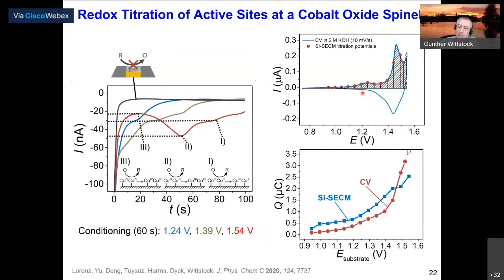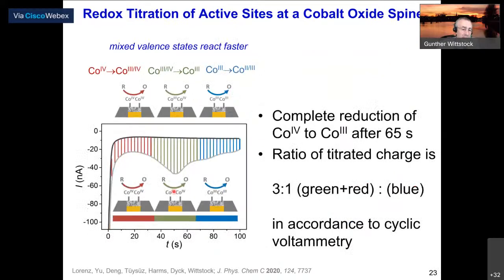If we go one step further until here, we see already a decay, then something which is going over another step, then a little bit more of that plateau, a decay, maybe even another plateau, and then decay to the baseline. If we go, however, here, then it becomes more interesting. We see a decay to a plateau like this, which is lower than the plateau measured before. Then the current rises to a plateau which is higher, then decays again to the same plateau as it was here, and then there. So we basically see a kinetic spectrum of the different sites which we can address or form at different potentials. And so here this is shown once more.